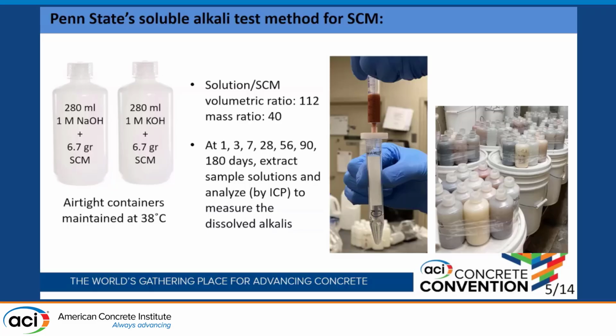A sample will be extracted from the bottles, filtered, and then sent for ICP analysis to determine soluble sodium and potassium. Separate bottles were dedicated for various ages to avoid carbonation and contamination during opening and closing the cap.